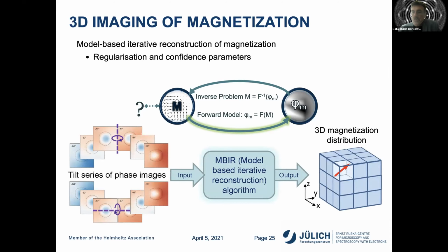That allows us to introduce regularization terms and confidence parameters, as well as the known location of the magnetic objects inside the field of view, and it allows us to introduce additional constraints and additional help from machine learning and to incorporate micromagnetic simulations inside the reconstruction algorithm, which would be difficult with a normal back projection based tomographic reconstruction approach. I won't show any results from this today, but it also works very nicely to reconstruct M in 3 dimensions.